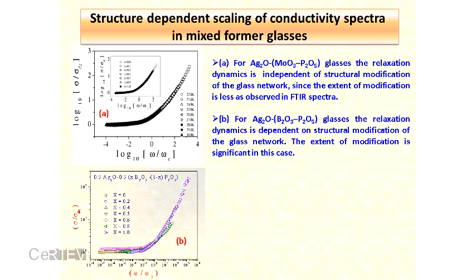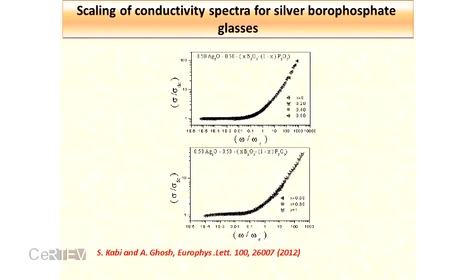But here for silver borophosphate glass, for which I have shown the results, you can see the superposition is not possible, because in the earlier systems, throughout the whole glass forming region, there is one type of structural unit. And for these systems, there are two types of structural unit dominating the conductivity. Because the population density of PO4 in a particular composition range is different from that in the other composition range, which you can see here.